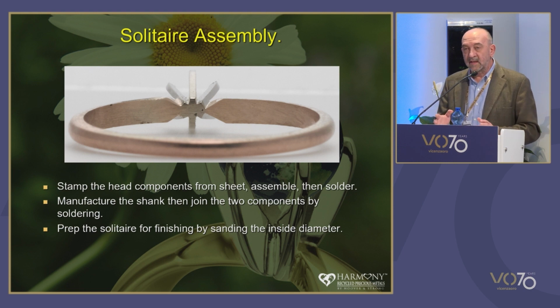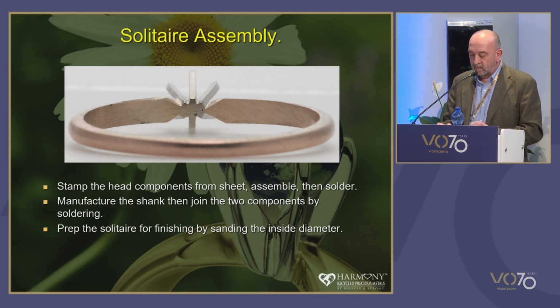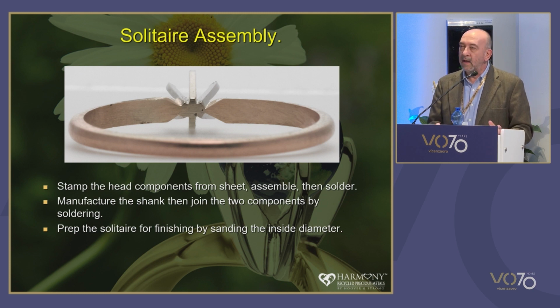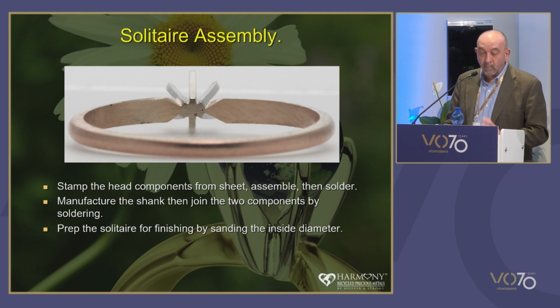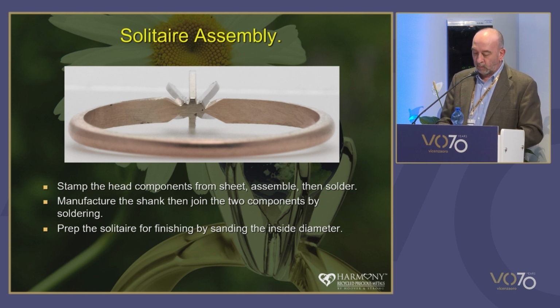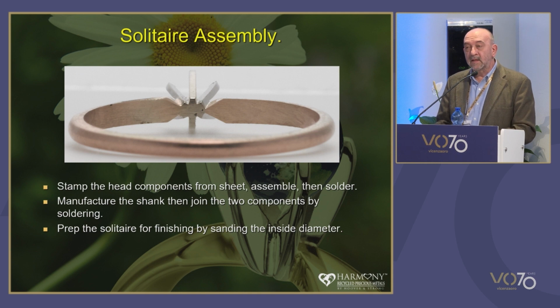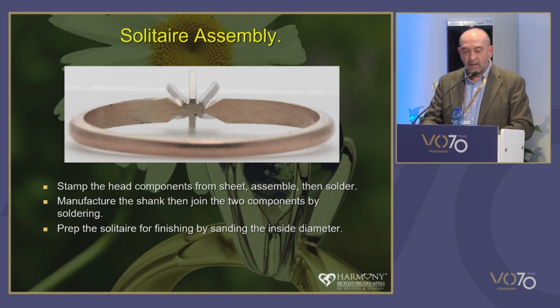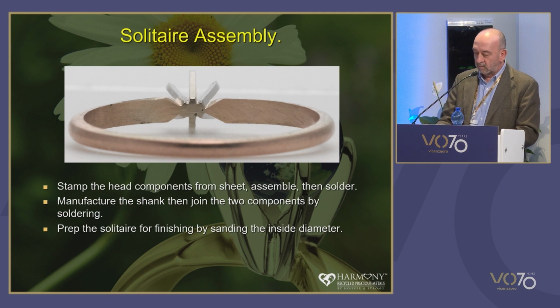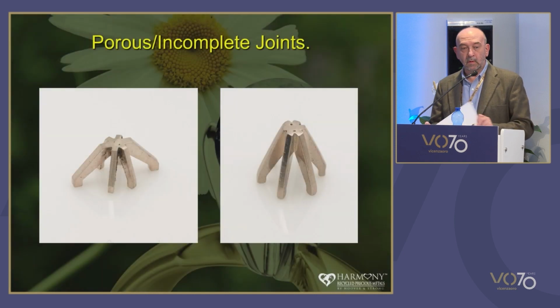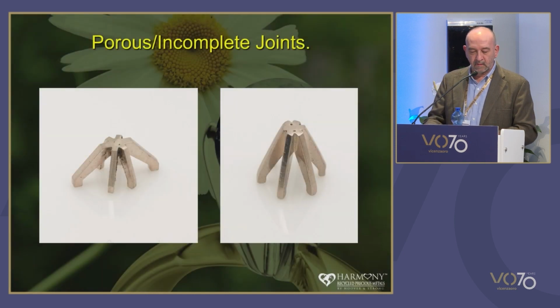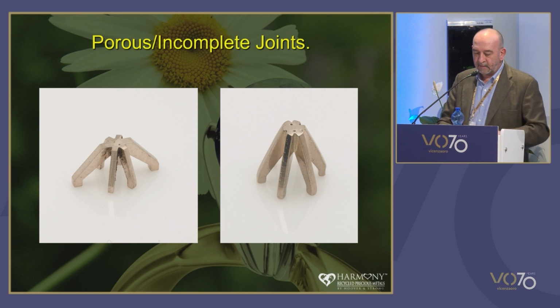And after inside sanding, our finishing department, they noticed that there was an increase in the incidence of porosity in the soldered area, and this was getting worse and worse. And it meant that more repairs were needed to make acceptable product, and therefore it was more cost and more time. Scrap rates eventually became unacceptable, so some investigation was needed. Here we have a few examples of rubbish heads.